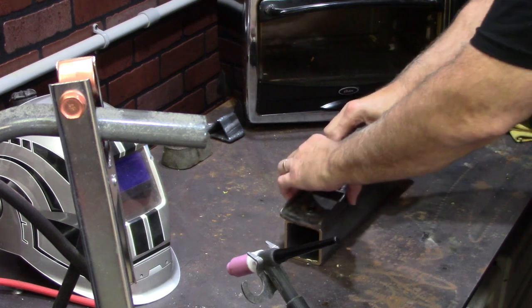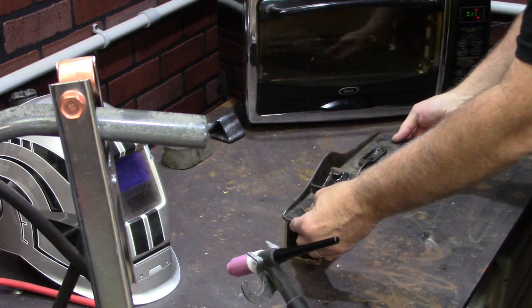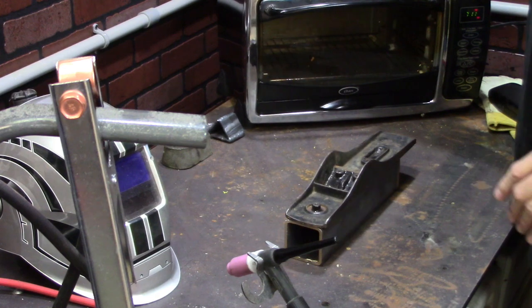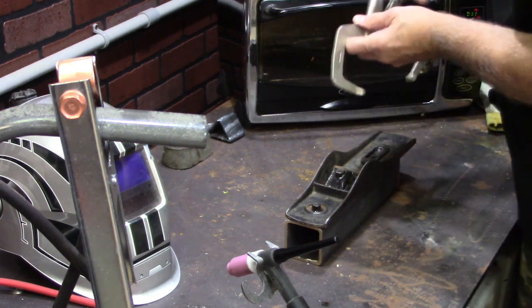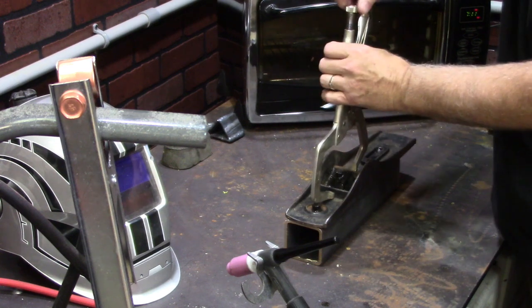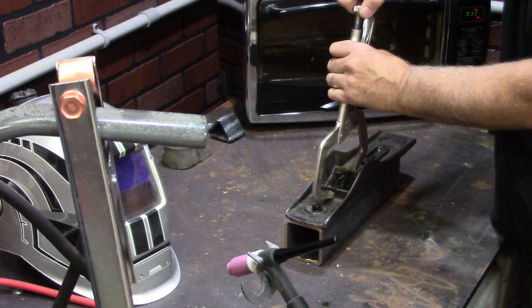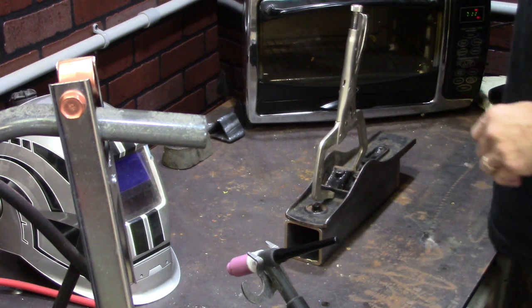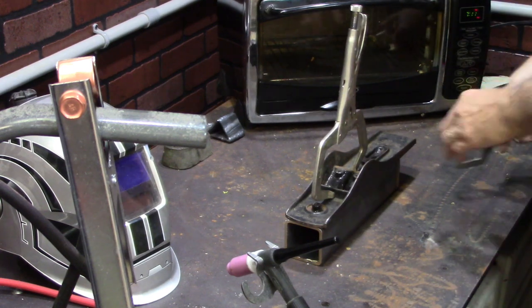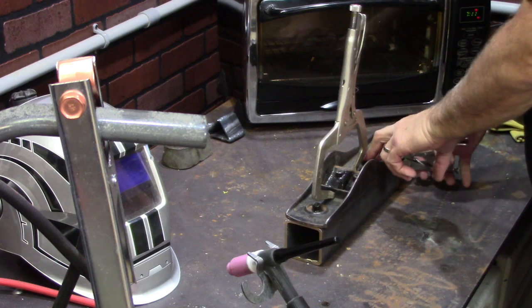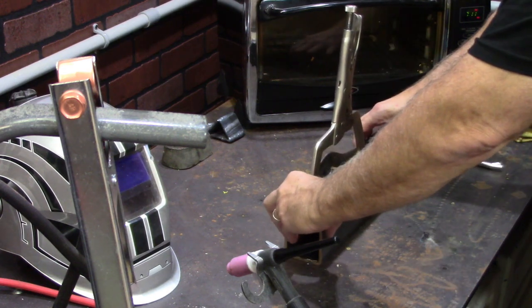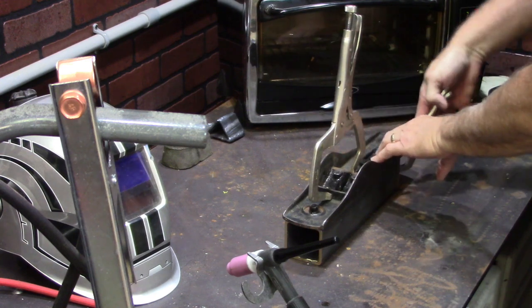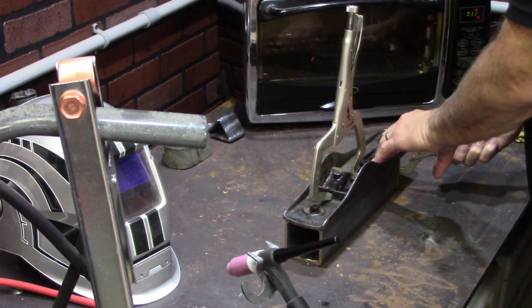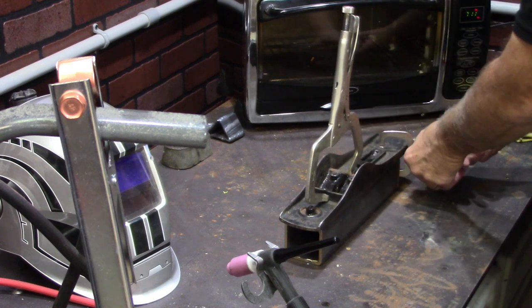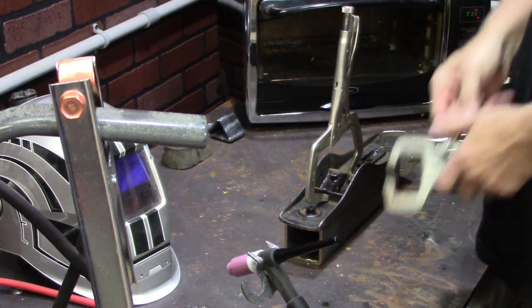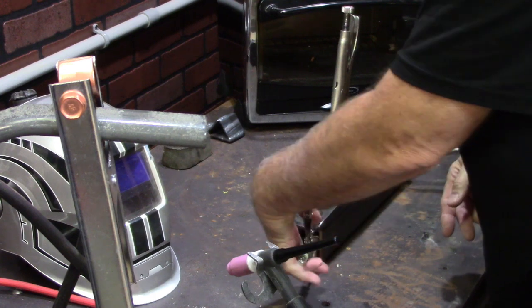Here I'm just mocking up the jig that I'm going to use to weld this piece of cast iron back together. I'm working this out ahead of time because this whole thing is going to go in the oven, and when it comes out it's going to be about 400 degrees. I don't want to be fumbling around trying to figure out how to clamp this thing together. At the same time, I don't want that cast to cool off too quick while I'm trying to weld it. I tried welding cast many years ago, a complete disaster. And this is a chance to try and learn to do this.